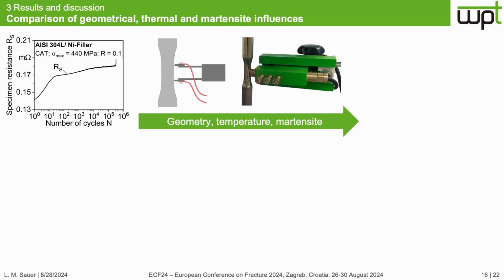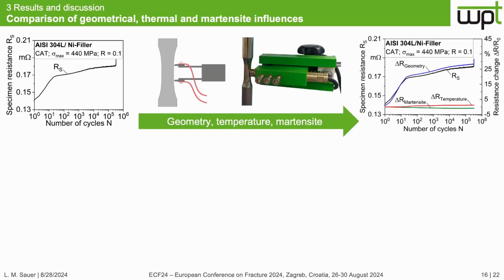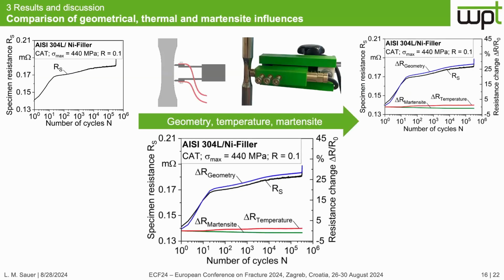And in addition, this method also allows the evaluation of the individual influence of the geometry, temperature, and martensite on the electrical resistance during the fatigue test. And as a result, the geometry has the highest influence on the electrical resistance because of the stress ratio of 0.1 and the high ductility of the used base material.